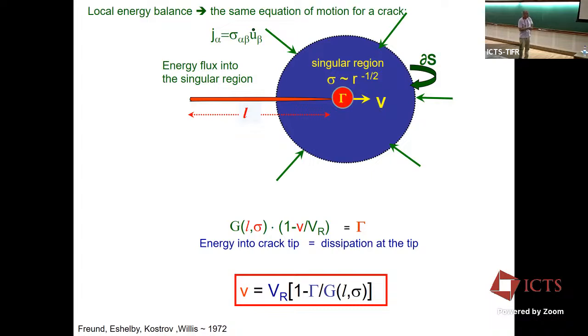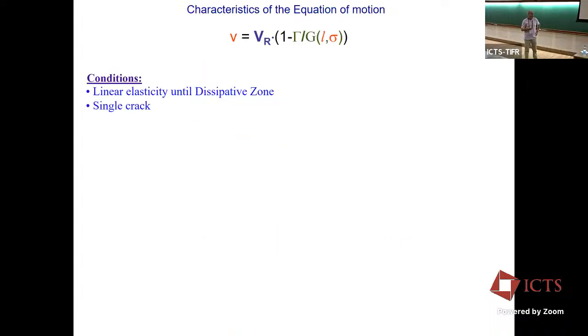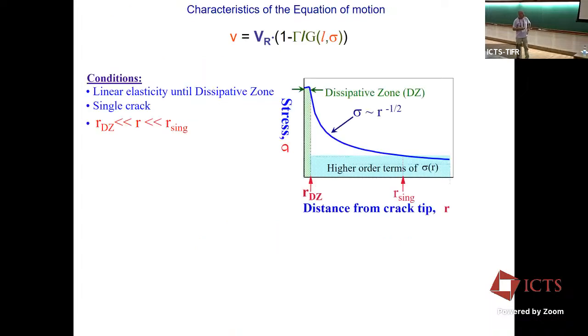So again, you have here the Rayleigh wave speed, 1 minus gamma, divided by the energy flux per unit area into the crack tip, which is G, and that's a function of the instantaneous length of the crack and the stresses that you apply far away. Okay, so some of the miracles of this equation of motion. We've assumed linear elasticity until dissipation. Here's a scale where dissipation takes place. So linear elasticity dominates near this singularity here, near where it's trying to become singular. It gets cut off somehow near the tip, at R equals 0, where dissipation takes place.